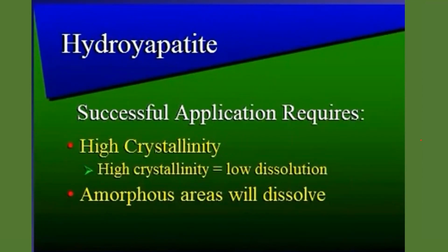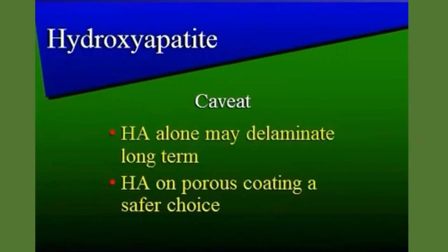Successful application requires high crystallinity. High crystallinity, low dissolution. Amorphous areas will dissolve. So you have to pay attention. The caveat, hydroxyapatite alone may delaminate long-term. Hydroxyapatite on porous coating is a safer choice. This is what I'm telling you.